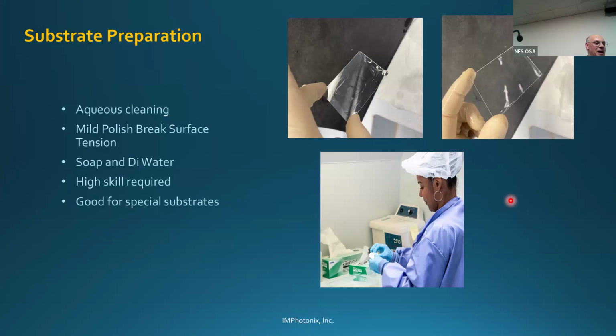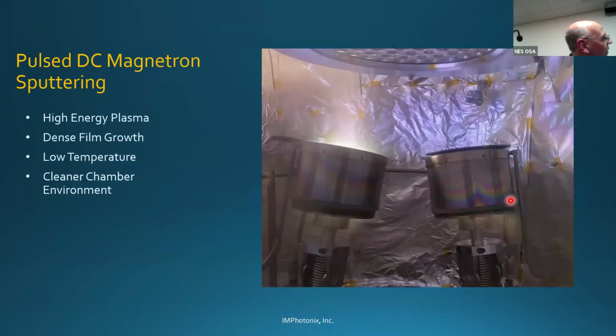And so you use argon gas on the sputtering for the tantalum, but you would introduce the oxygen through an oxygen distribution ring. Well, if that shows it there. No, this one doesn't have it. We've added it later. This is our tantalum target here. This is an argon distribution ring, but we have actually put in another oxygen ring near the substrate. So we're actually evaporating tantalum metal, and we're creating tantalum oxide right at the surface of the substrate.